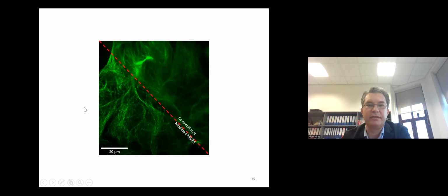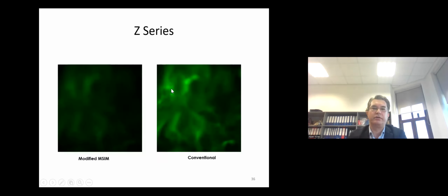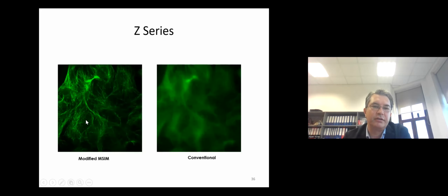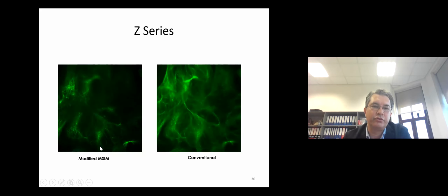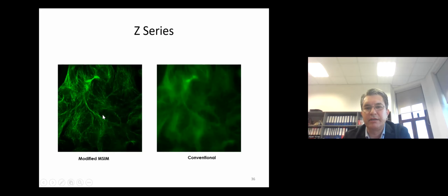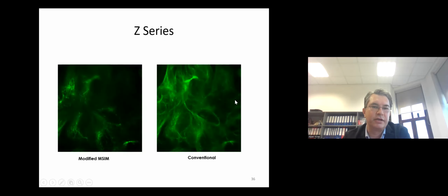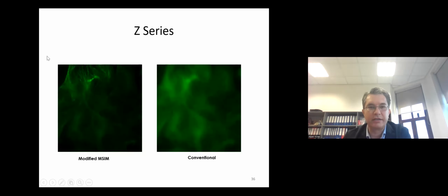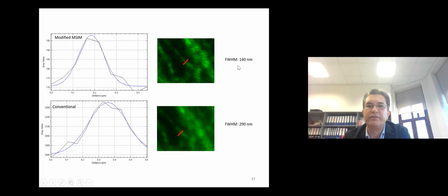So we have implemented this and obtained the higher resolution, this image scanning microscopy resolution, and also we achieved the higher Z resolution. So on the left, you see our modified image scanning microscopy algorithm, and this is the wide field fluorescence algorithm. So you can clearly see the improvement in transverse resolution and also in axial resolution. So we went down to 140 nanometers in the full width at half maximum of the microtubules that we recorded,